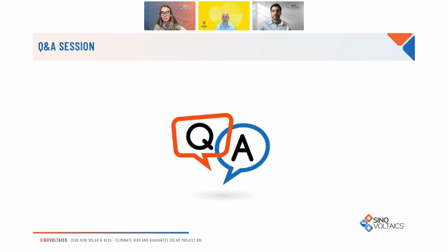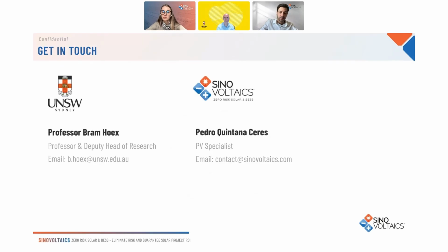If it's relating to extreme weather events, I would not know the exact answer to that. Of course, if you keep a module inside, it will not degrade a lot. So I think most of the degradation is because it is exposed to the elements. Extreme weather can result in catastrophic failures where a significant part of the power plant is taken out. But we definitely see that almost all failure modes, like corrosion and UV-ID, scale with the stress factor. Doubling the dose is maybe not doubling the degradation, but degradation will definitely scale.